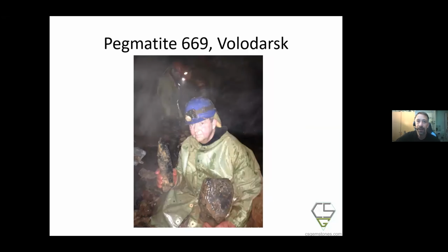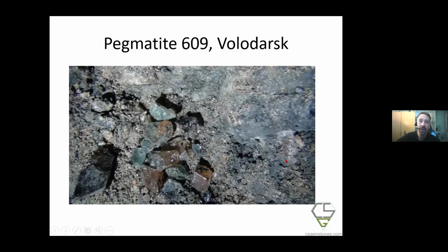Well, one of our guests here comes in. This is how I can be sure that some or many of my specimens are natural, because I know the guy who pulled them out of the ground here, Peter Lickberg, carrying a 30-kilogram topaz in the small smoky, and here from another pocket, which is called the gem pocket in Volodarsk, you see the specimens directly, freshly out of the ground. And if you have this, what I call the pedigree from the miner, the finding directly to the mineral and to the cut stone, then you can be sure that there have not been any treatments done to your gems.